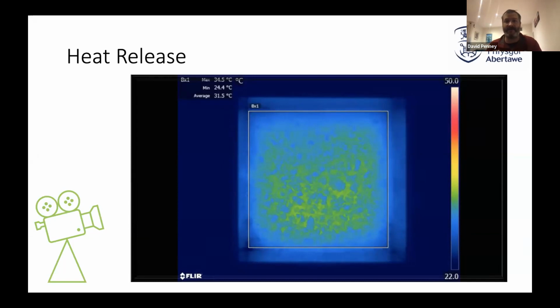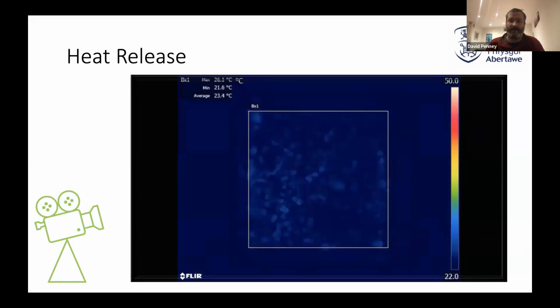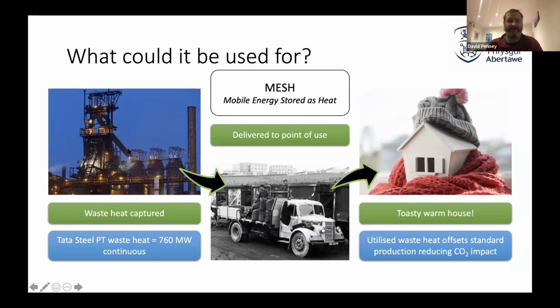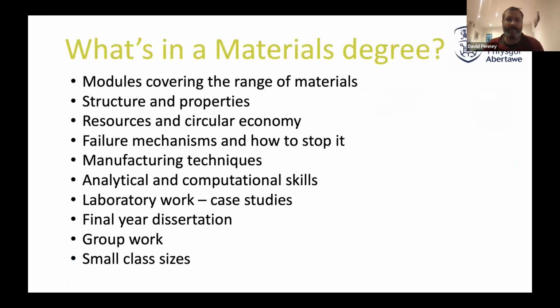So if you think about it, you could store heat indefinitely. You just take a big box of this vermiculite, which has been dried out with the heat, and then you use it when you're ready by putting cold, moist air in, and you get the high temperature out. You could take the waste heat, say from Tata Steel, and put it on the back of a van in something the size of a fridge, and then use it to warm your home. That's the plan for some of the work we're doing at Swansea.